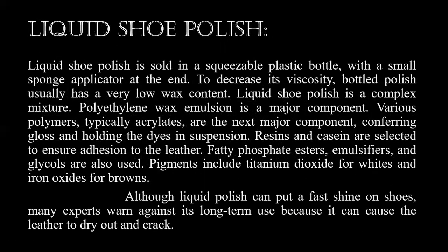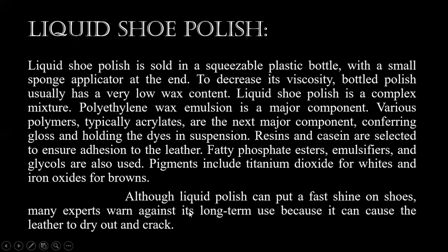Liquid shoe polish is sold in squeezable plastic bottles with a small sponge applicator at the end. To decrease its viscosity, liquid shoe polish has a very low wax content. It is a complex mixture — polyethylene wax emulsion is a major component, and various polymers, typically acrylic, are the next major components, conferring gloss and holding the dyes in suspension. Resins and casein are selected to ensure adhesion to the leather. Fatty phosphate esters, emulsifiers, and glycols are also used. Pigments include titanium dioxide for whites and iron oxide for browns. However, although liquid shoe polish can put a fast shine on shoes, many experts warn against its long-term use because it can cause the leather to dry out and crack.